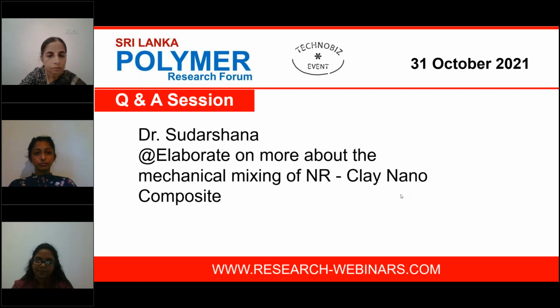But the thing is, the mechanical friction we apply to our composite is very difficult. When friction is generated, the clay layers have a chance to separate. But a normal clay particle may be around 8 microns, with about 3,000 clay layers, so it's very difficult to separate the clay layers. At least if we can get the clay stacked with 10 or 20 layers, that is also good, but it is very difficult to separate clay layers by that.